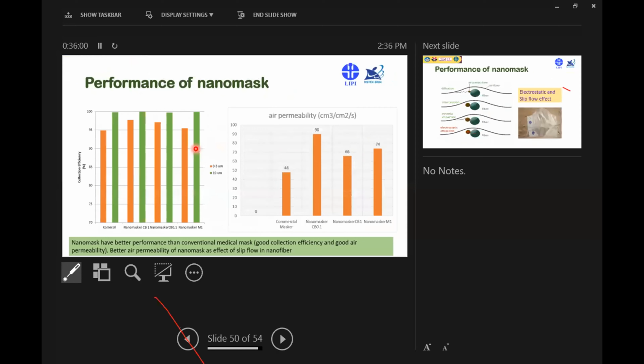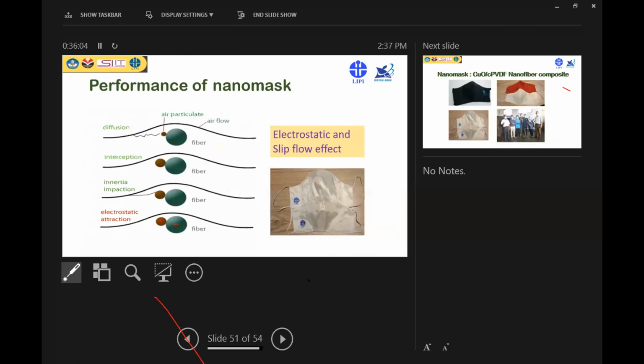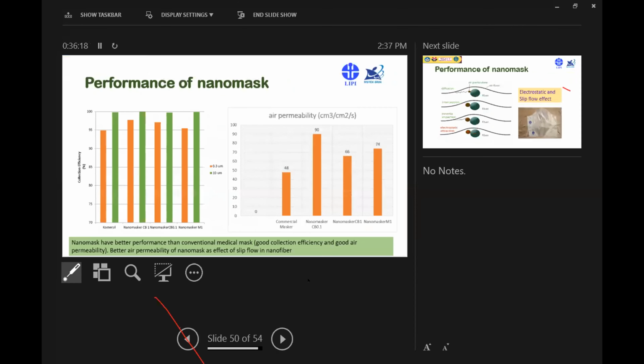So why do we get this result? An important factor is the electrostatic attraction in our material, because we use piezoelectric material which has the beta phase crystal structure. So we can get better collection efficiency than the conventional mask.